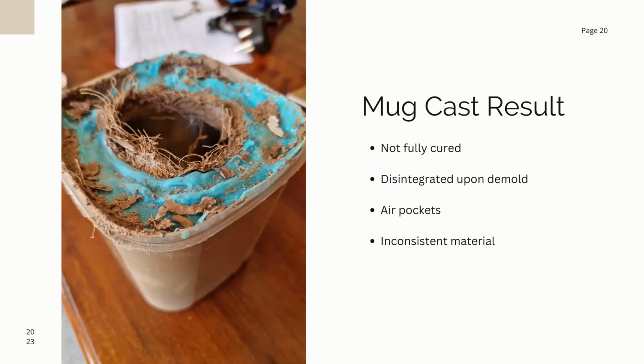So we let the biomaterial sit within the mold for about 48 hours, and we decided to finally take it out because we thought after 48 hours it surely must be properly cured. Turns out it was not properly cured. We took it out of the mold and it completely fell apart. Most of the bioresin was not fully cured at all, so it was quite a bit of a sludge and a bit of a crumble.